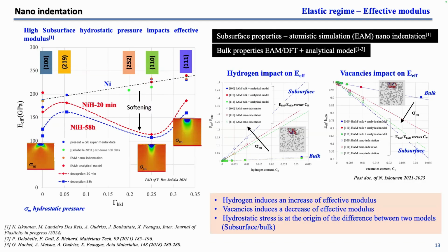To question that, we use atomistic calculation and show that the softening of the elastic modulus is not linked to the concentration of hydrogen, because hydrogen concentration increases elastic modulus, but it's induced by the production of vacancy. When we add a vacancy in the box, we show that we have a softening. And the effect is larger in subsurface than in bulk, because we have a large elastic pressure in the surface during indentation.